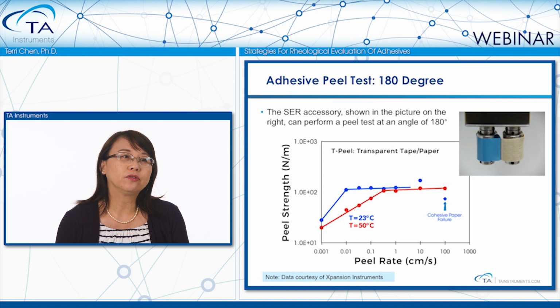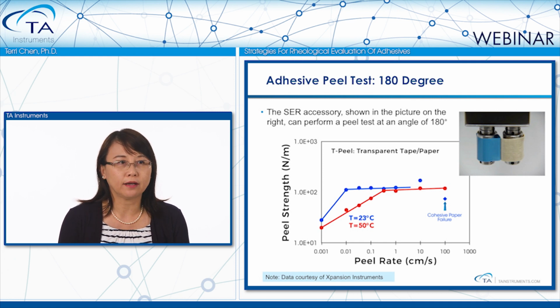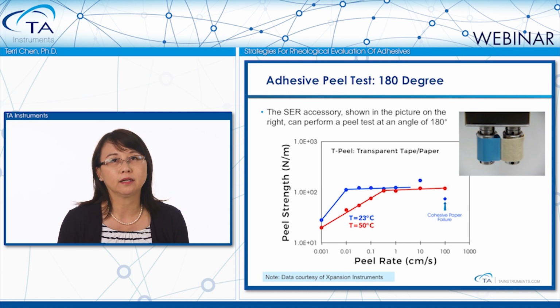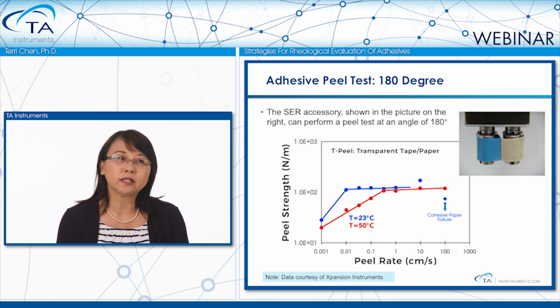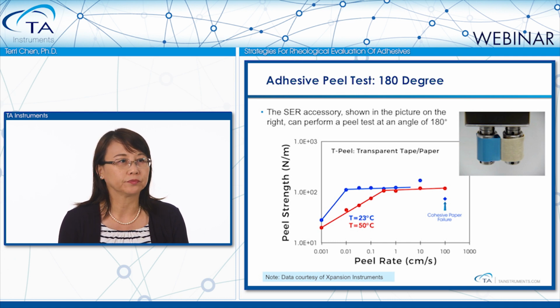Peel tests are usually conducted at different peel angles, such as 90 degrees or 180 degrees. Using a SER geometry on a rotational rheometer, we can easily perform the peel test at 180 degrees. The peel strength can be measured at different peel rate and also with different temperature.